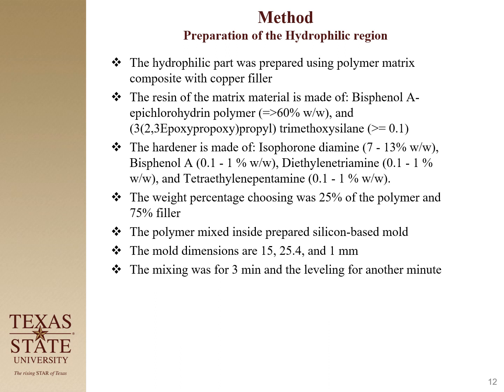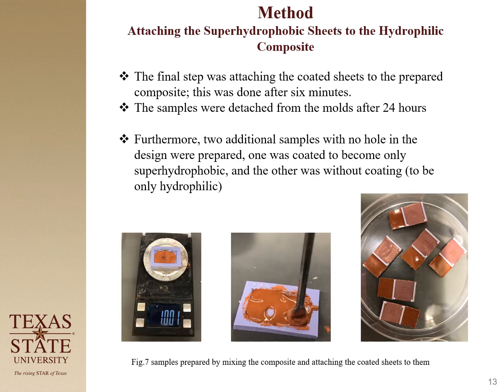I made a mold and I put all the mix together and mixed them for 3 minutes manually with a spatula, then leveled for 1 minute. Then finally I attach the coated sheet to the composite, which, of course, is hydrophilic. And of course, you can see that there is an extra part. That part I clip off before testing my sample.